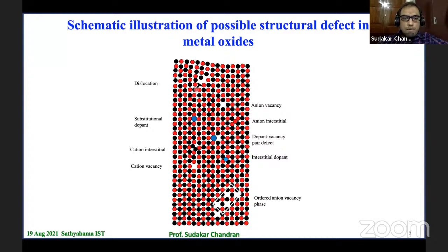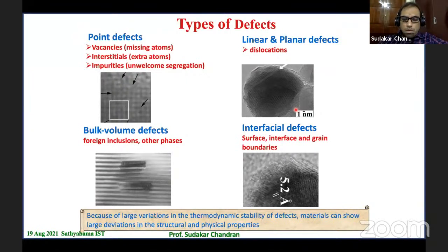In addition to these, you do have dislocations and various other line defects, planar defects, and so on. The concentration of all of these in a given crystal structure is going to affect the properties. Of course, this is the schematic I showed. Let me give real pictures. Here is an example of a point defect. These are high resolution images of some of the oxides. You can see that it is supposed to be a perfect cube, but there are certain distortions in this place and here. Either they are stretched out or there is some kind of strain present because of the missing atoms. In this case, oxygen vacancies are present in the indium oxide matrix. Therefore, you can see locally, the missing atom introduces a lot of strain in the lattice.